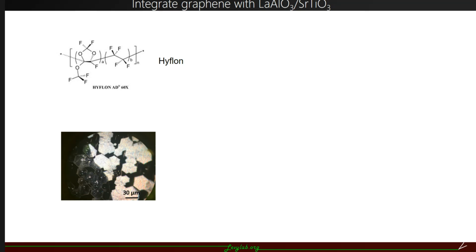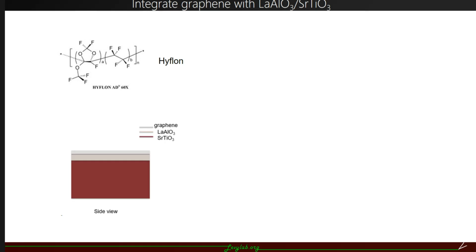So our goal is to integrate these two novel systems together. In our group, we grow CVD graphene ourselves and then transfer it onto the LAO-STO substrate. Instead of using the traditional PMMA, here we came up with a replacement called Hyflon. It leaves less residue on top of LAO-STO and supposedly has better transport properties than PMMA-transferred graphene. So here is the side view of our device. We put graphene directly on top of LAO-STO. The LAO can work as a barrier.